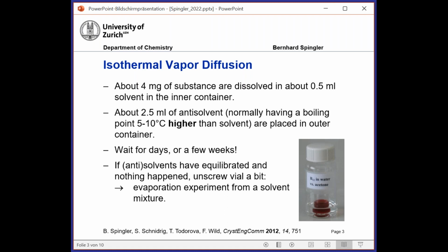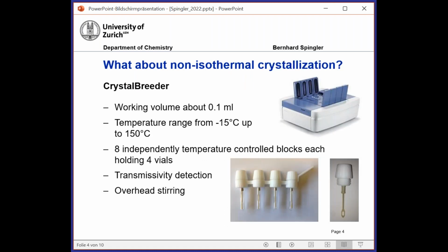We then wait for days or weeks, and you also saw in the presentation of Doris that some of these crystallizations take quite a while. If nothing happens, you can still unscrew the cap a little bit after these 2 weeks, and then you change from a vapor diffusion experiment directly into an evaporation experiment. So now the question is, what about non-isothermal crystallization?